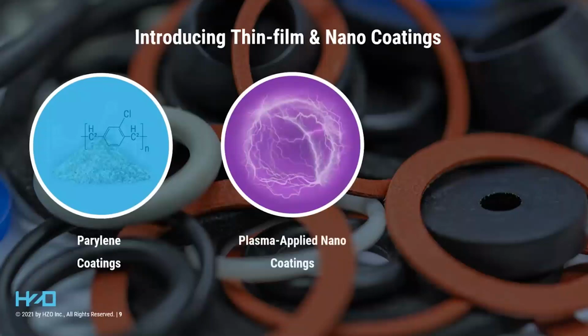Moving on to plasma applied nano coatings. These are deposited using plasma enhanced CVD, or PECVD. So it's just another subset of chemical vapor deposition. It also happens in a vacuum chamber. You can either create a remote plasma to create polymerizable species outside of the deposition chamber, or you can create plasma in chamber to create species just above the board, which helps with polymerization in situ on the board. Plasma can facilitate a huge range of materials, from polymers all the way out to ceramics, using carbon, silicon, and metal oxide-based chemistries.